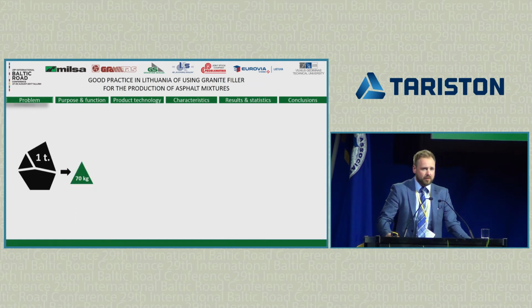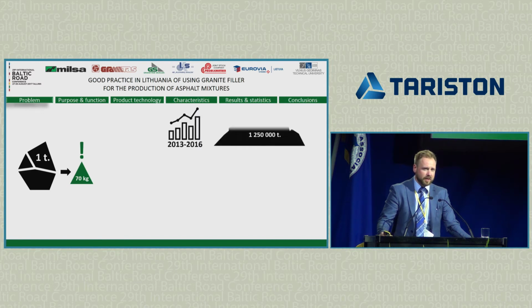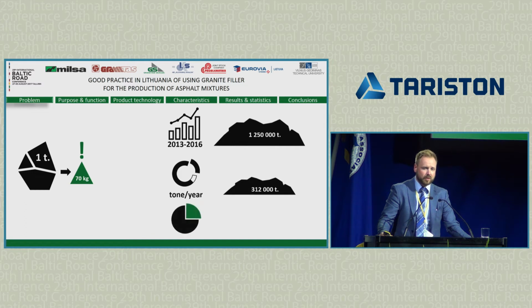So if we talk about the problem, the amount of the problem, we can say that granite fines make approximately 70 kilograms per ton of granite production. So if you believe the Lithuanian statistics, between 2013 and 2016, granite of fraction 0 to 16 on the market took about 1,250,000 tons. So it makes about 312,000 tons per year, and it makes around 22,000 tons of granite fines per year.